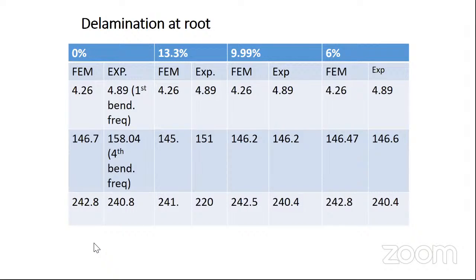This figure shows the area of the delamination. Only one case we have considered. If the delamination is at the root, from 13.3% of the total area down to 6% of the total area, what delamination can we find? From this we can see that as we go to higher frequencies, it is easier to find the delamination. This is a very preliminary study we have done with some BTech students.